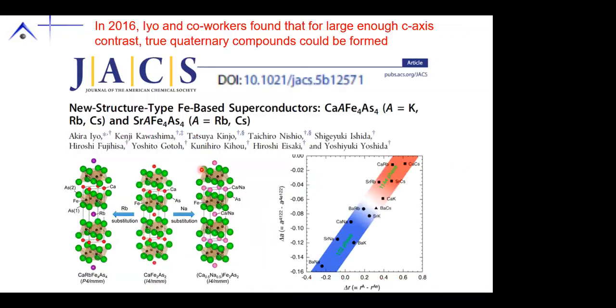Okay? So in 2016, Iyo and co-workers found that for large enough c-axis contrast, you could take these 1,2,2 arsenides and create a true quaternary, a 1,1,4,4. So if you mix calcium and sodium or barium and potassium, these are systems that are close enough in size that you get a solid solution on the alkali earth site. Okay, so it's still the 1,2,2 structure.